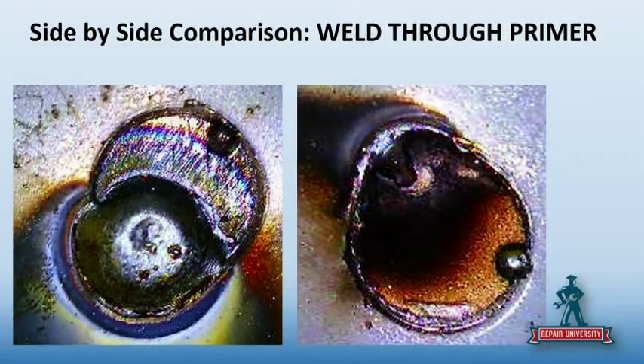All right, so let's go, because I think weld-through primer is one of the things we do wrong the most in this industry. Shawn, walk us through some of the comparisons and the stuff you brought us around weld-through primer. Well, this is interesting because I did some high-resolution photography of the initial first strike of the arc when you pull the trigger with your MIG welder. The picture on the left is showing bare steel, where you're welding the bare steel. And technicians know this instinctively. If it's completely clean, they pull that trigger, and that first little globule of molten steel from the wire just jumps right onto the steel, and you can see you get good fusion all the way around it.